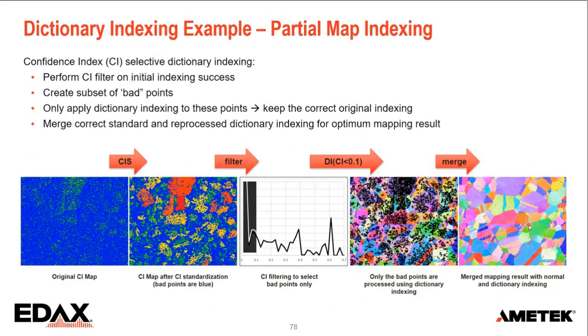You can use the very fast Hough-based indexing for the initial work, and the points that happen to index okay, we can use those. And then you apply the dictionary indexing to the points that refuse to index, because we just couldn't find the bands properly, and then we can get a good indexing result for everything.